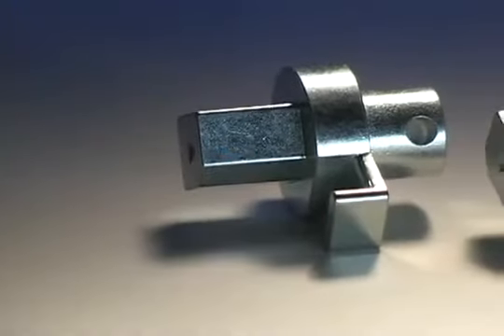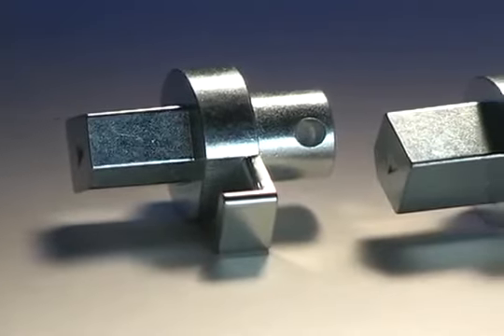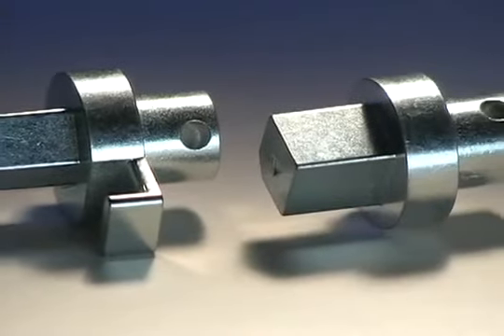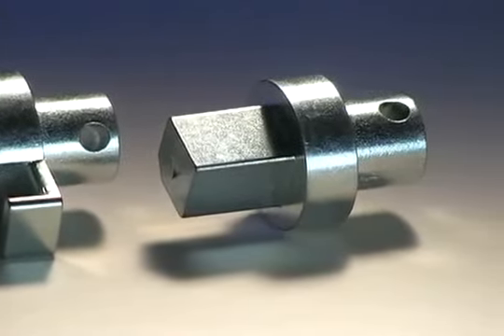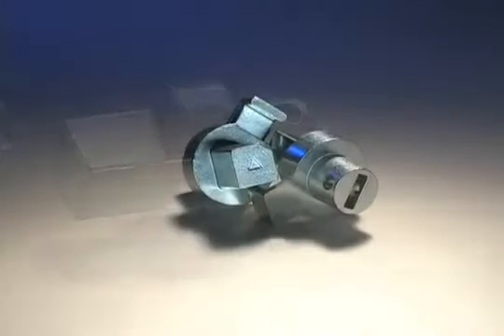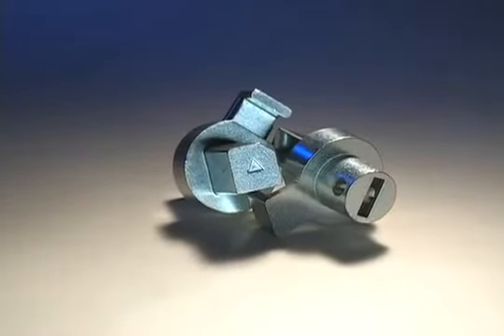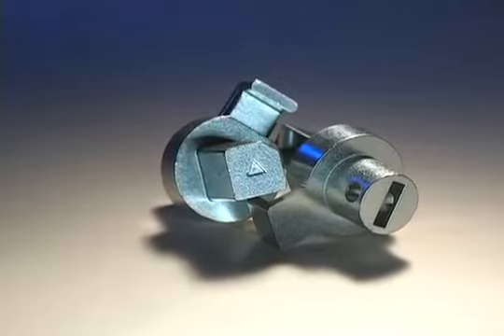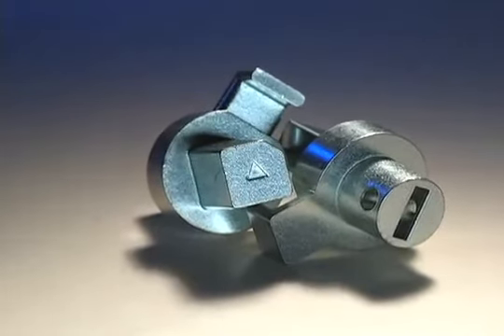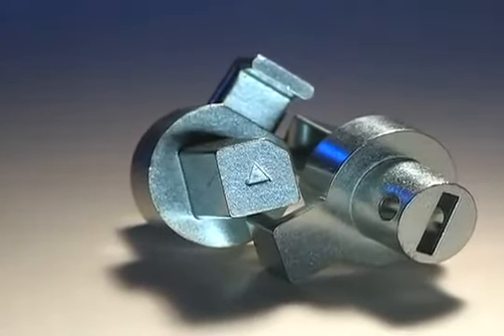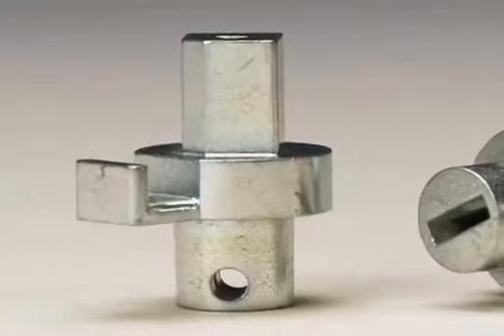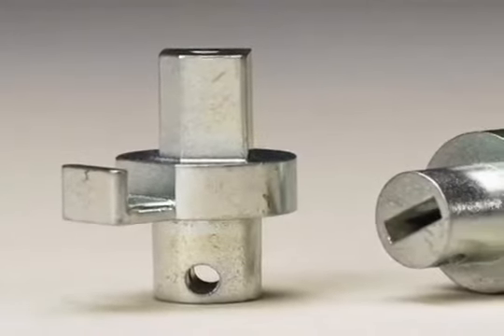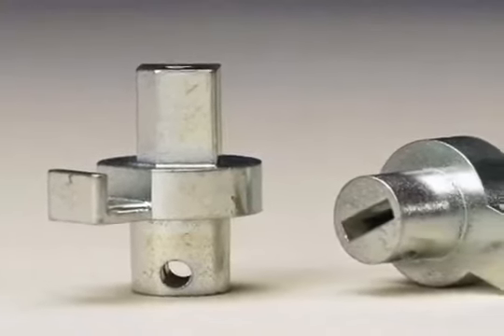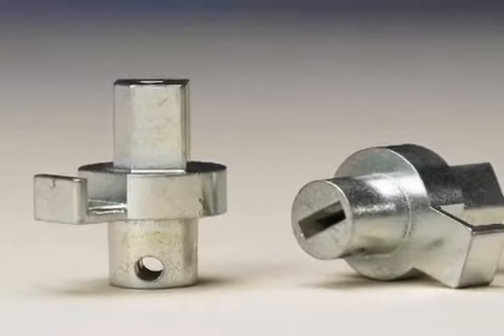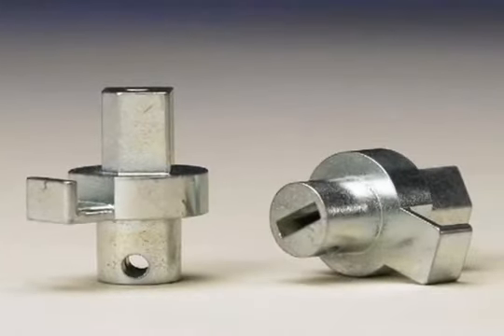The PM spindle is made to 7.7 grams per cubic centimeter density and has a 95,000 psi ultimate tensile strength, 8% elongation, and 90 HRB hardness. The PM process allowed 95% materials utilization as opposed to machining a wrought blank, which yields a materials utilization figure of only 45%. PM also provided a 90% energy savings.